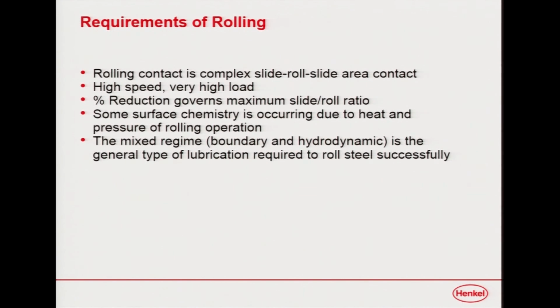It's very high speed. It's extremely high load, because let's face it, you don't squish steel with your fingers. And the reduction, so the percentage reduction, this is how much reduction we take in the strip. This is what governs how much we can squish it, because it can only go so fast out of the back end and only so fast out of the front end. If you squish it too much, eventually it actually starts to back up, and you get these little bumps in the steel as it goes, and the thickness varies very dramatically over the surface.